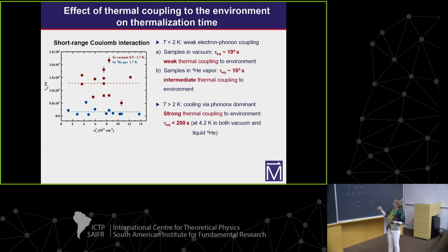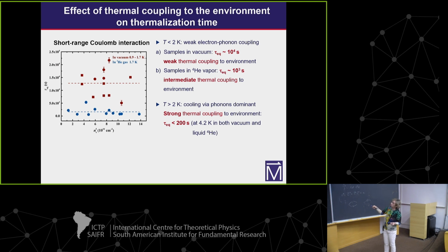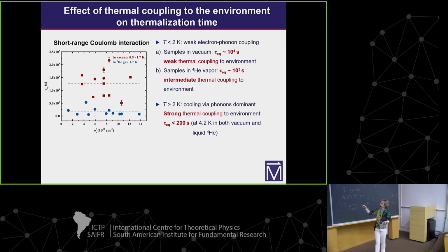Now, if you go to higher temperature, here phonons become important. We have strong coupling to the environment, and we also performed some experiments, and we got the upper bound for the thermalization time, tau, to be 200 seconds. This was reduced by another order of magnitude, and this did not depend on where we placed the sample, vacuum or liquid helium, and this makes sense because the dominant coupling is really to the phonons.